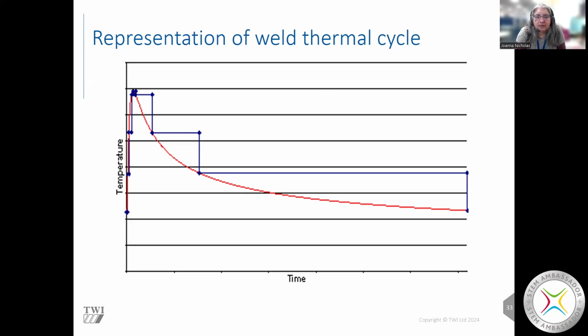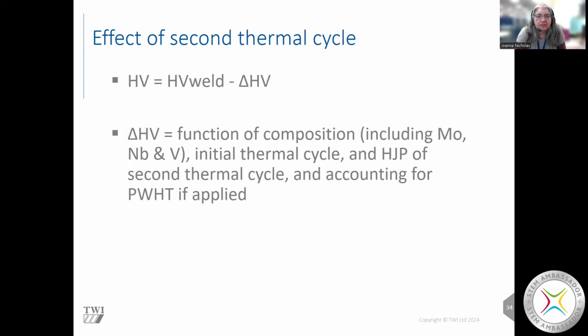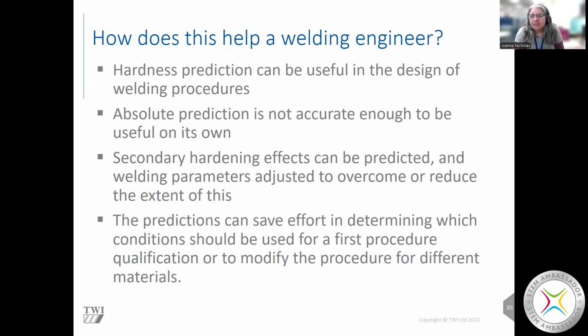So each of those steps represents a post-weld heat treatment, and then I can use that same approach that says the hardness is the original hardness minus a change in hardness, and that change in hardness depends on the composition, the initial thermal cycle, and the Holloman-Jaffe parameter H of the second thermal cycle, and if we've got post-weld heat treatment, that as well. Well, how does that all help a welding engineer? Well, we're back to that hardness prediction to try and get to a particular welding procedure.